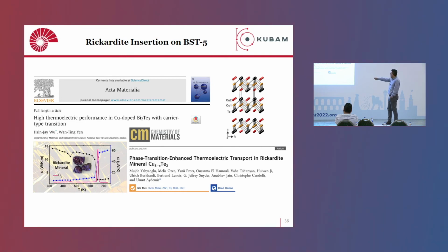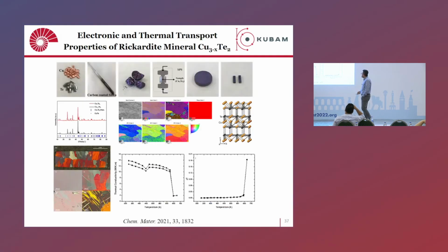And while we saw this paper, we were basically doing another research on copper telluride. So this copper telluride is a synthetic Rickardite mineral. It shows nice properties, like here. You can see that you can straightforwardly make it with solid-state synthesis. You see that this is a very good crystalline, purple-like crystalline material. So you can make it with this method. And the crystal structure is also kind of layered-like. It doesn't show here, but it is a layered-like structure. So here you can see that we have very nice grain distribution.